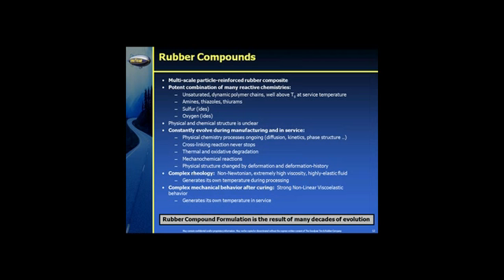Now I'm going to spend the remainder of my time talking specifically about some general areas. What I want to give you here is a raft of challenges that are facing us, and then some more specifics in selected areas. So looking more closely at rubber compounds we typically use, they comprise the following on that chart. And as the earlier chart illustrated, there are different length and time scales at play. For instance, in carbon black, that runs from scales of activity at the tens of nanometers to hundreds of nanometers and then into the micron scale. We've got a lot of reactive solid-state chemistry taking place, and the rheological and mechanical behavior is also complex.